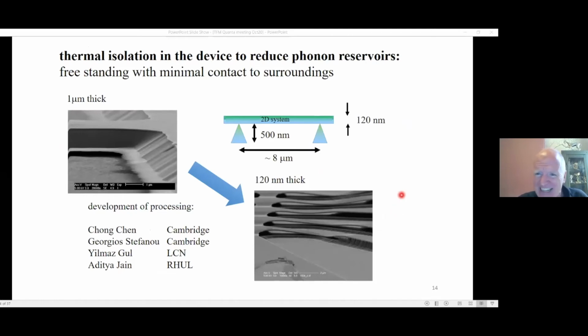Going back to the InGaAs, what happens when we take the thicker layers, but grow new devices and make them thinner? We calculated that we could study a 2D system that's about 120 nanometers thick if it was no more than about 8 microns in size. And this is what happens here. This is a strange angle SEM image, courtesy of Georgios in the Cavendish. This is the Hall bar channel here, and these are potential arms that contact the channel for measuring voltages or currents, voltages, impedance. You can see where the sacrificial layer has been etched away and partial collapse. So we already know that even at 8 microns, we're kind of pushing how these devices will stand up.